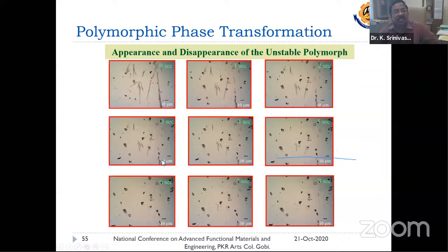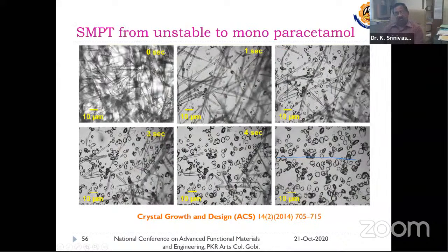This is another solution mediated polymorphic transformation from unstable to monoclinic paracetamol. See here, both polymorphs exist. Only the unstable form exists here, and in between there are nucleations of the stable monoclinic forms. These monoclinic forms are continuously growing, while the needle-like unstable polymorph is continuously dissolving. So, complete transformation of the unstable to the stable form. This is known as solution mediated polymorphic transformation.